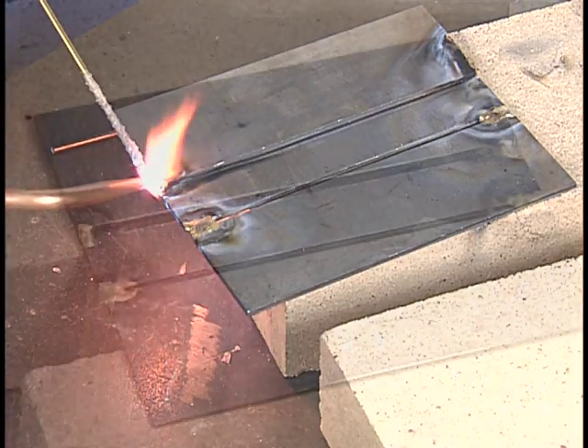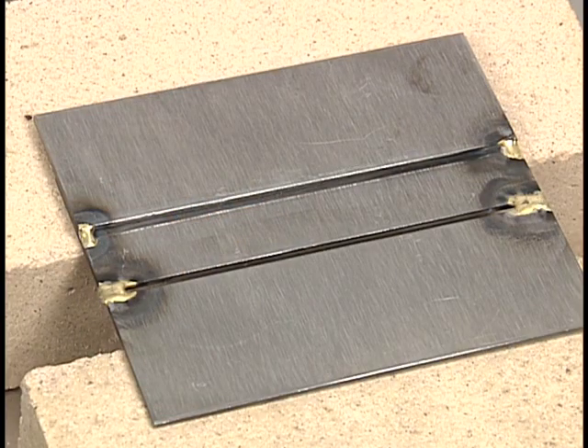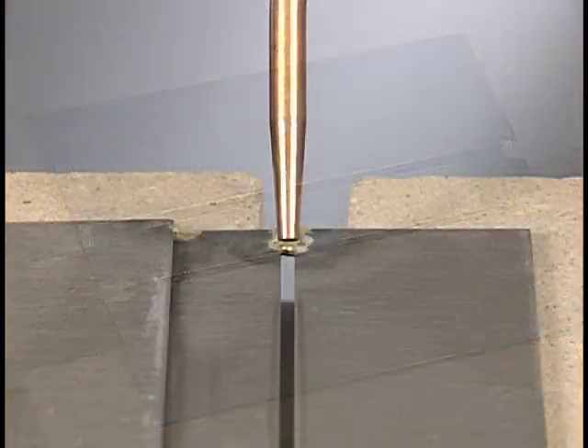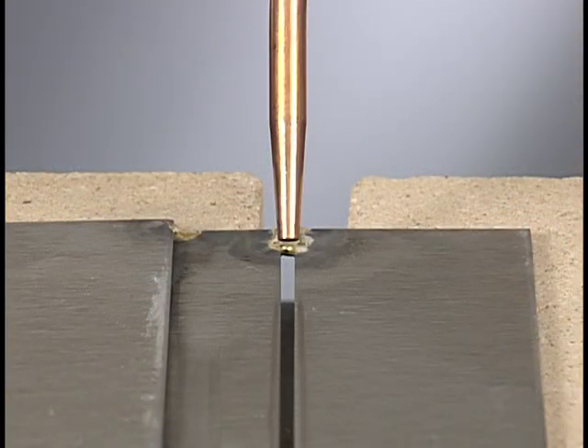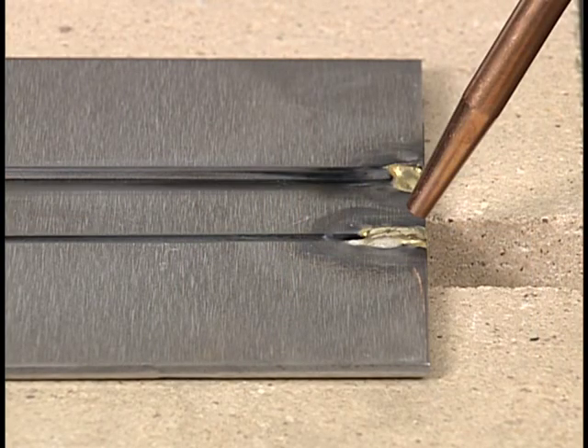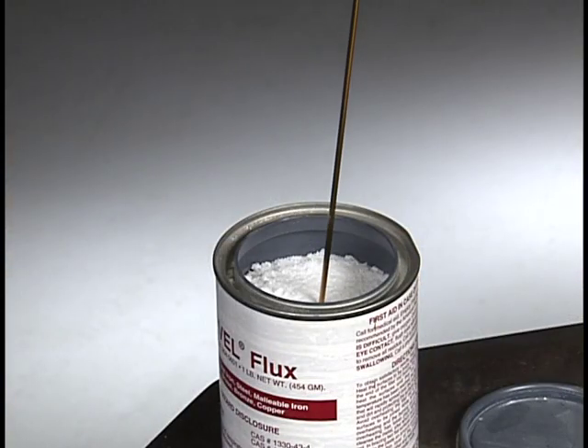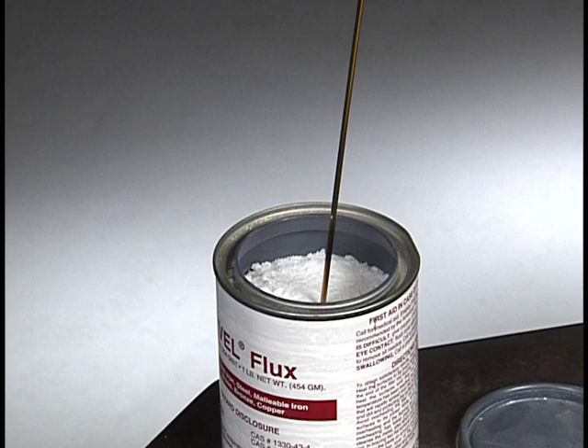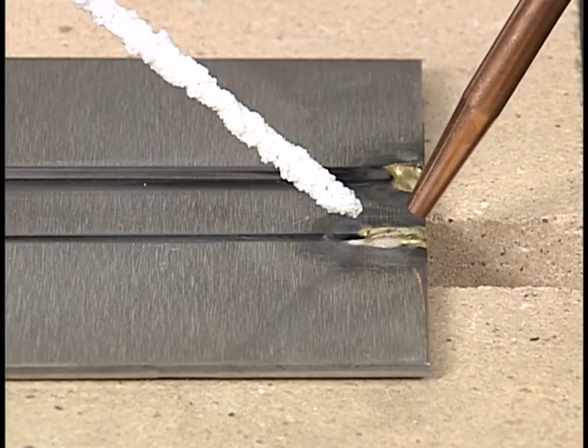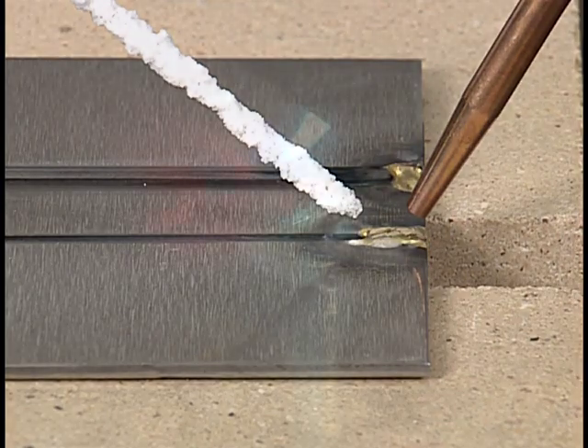Place the workpiece on the fire bricks in the flat or 1G position with the square groove joint centered over the space between the bricks with the lap joint facing up. Position the torch on the tack weld with a work angle that is approximately 90 degrees and a 25 to 30 degree push travel angle. If you are not using a pre-fluxed rod, dip the heated filler rod in flux. Then position the rod over the axis of the joint at approximately a 45-degree angle.